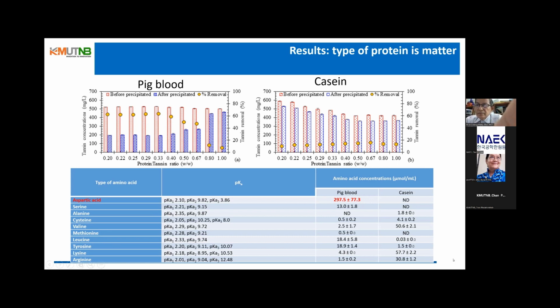Similarly, at the optimal pH for the removal of tannins by casein protein, the amine groups of lysine and valine can be positively charged. However, the difference between the pig blood and casein could be due to the proportion of amino acids that can interact with tannin to form the protein-tannin complexes. That is, the proportion of aspartic acid in pig blood was about 5 to 10-fold more than the proportion of lysine, valine, and arginine in casein.